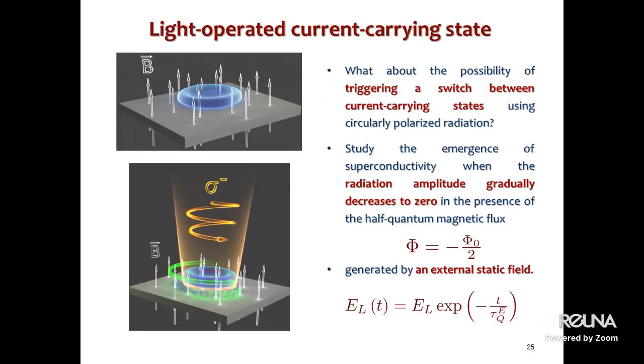So I add a half flux quantum to the system on top of circularly polarized light, and then I evolve the system for time larger than zero. And for that time, I apply external illumination. Basically, at time equal to zero, the system is in the normal metallic state. Superconductivity was destroyed by strong illumination, and then the illumination is switched off and the amplitude decays exponentially. The characteristic decay time is tau e.